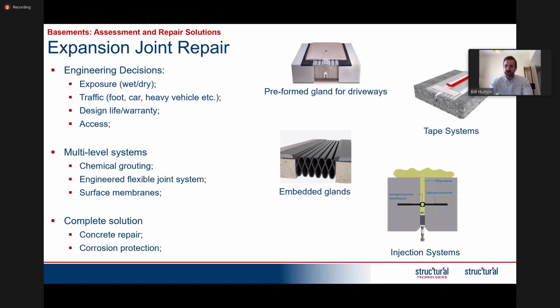So, you have two options there. One would be to repair it from the bottom. One would be to repair it from the top. The best way to repair it would be at the source. So that would be to actually remove all the landscaping, remove the tiles, and actually get back down to the joint and repair it from the top. If for some reason that's not possible and you have to repair it from the bottom, then certainly it's possible, but it could end up being more complicated, and you may face some challenges along the way.